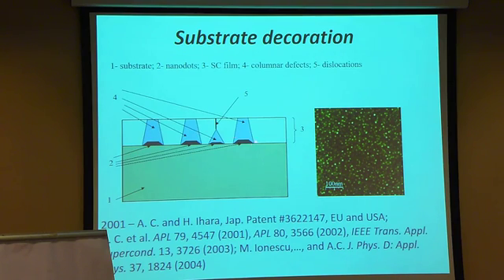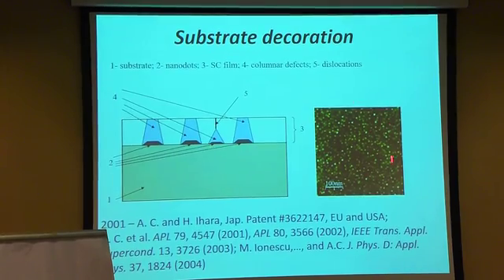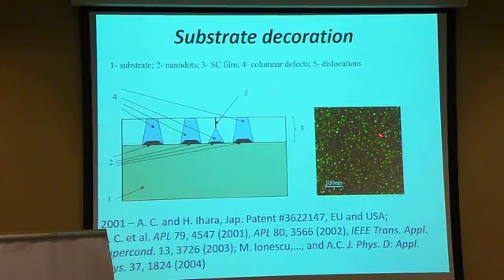Okay, so the first cost-effective method of creating this is quite an old one. When I was working in Japan with Hideo Ihara, he was trying to grow thin films based on the thallium system. Of course, that is now gone because thallium is too toxic and volatile to be used. But anyway, the idea was to deposit nano islands on certain materials in such a way that when we started the growth of the superconducting film, on top of these nano islands we create defects or columnar defects, columns of non-superconducting material, or if the superconducting film returned to growing, we have dislocations. So this is an AFM image of nano islands of silver on the substrate before growth.